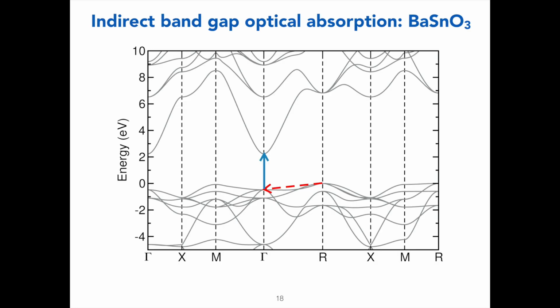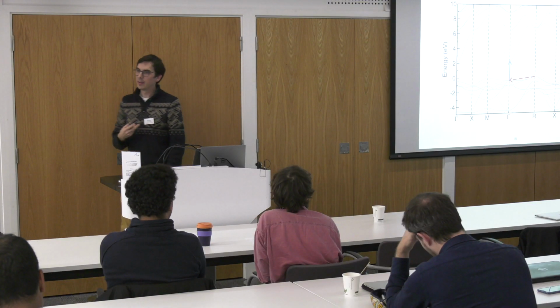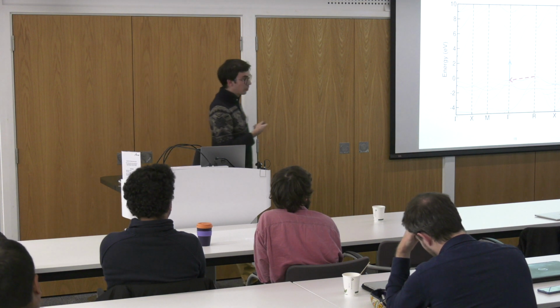This is just an example of a band structure of an indirect band gap material. This is barium stannate, a material that's of some interest for transparent conducting applications at the moment. The reason is that it has a band gap here, which is just above the visible. And then, crucially, it has another big band gap here, such that if you dope this material, placing the Fermi level here, it can conduct, but at the same time it's transparent, because the excitations from here to here and also from here to here are above the visible. These transparent conductors are very useful. You pretty much have them in all mobile phones, for example.